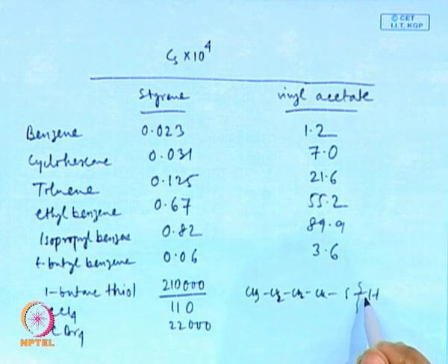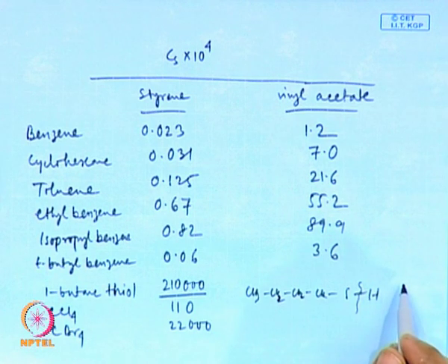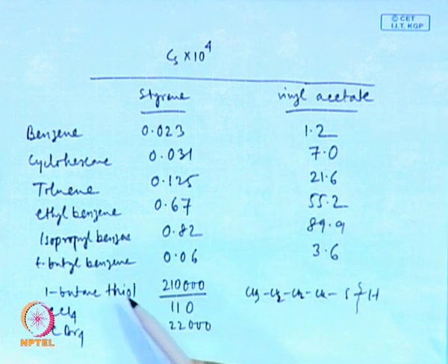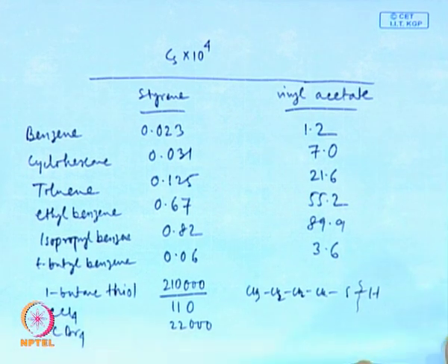Okay, so this hydrogen can be very easily abstracted by the propagating radical. So, by using this type of chain transfer thiols or dithiol compounds, you can reduce or control your molecular weight to a value of your choice or your target.